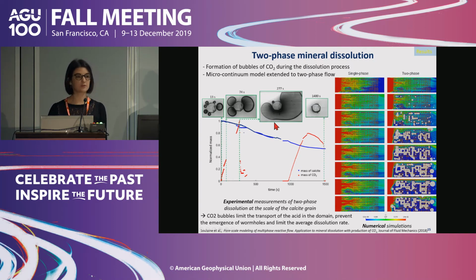And we observe the same successive events with a numerical simulation. So experimentally, we are able to measure, again, the mass of calcite with time. We can also measure the mass of CO2 with time, and we can also measure, I did not show it here, the size distribution of the bubbles with time. And so with that, again, we were using the experiments to validate the numerical code, and then we were able to perform simulation for the same kind of porous media that I was showing before.